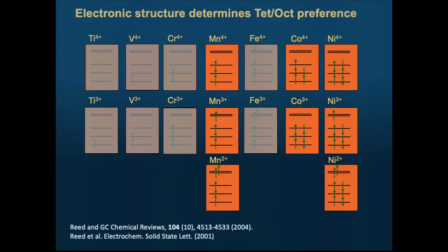What about manganese 3? You think maybe that would be OK. The problem you have with manganese 3 is that it disproportionates. It makes manganese 2 and manganese 4 sometimes, and manganese 2 is terrible. Five electrons, it's a half-filled d shell. This thing moves all over the place, because basically it's ambivalent about its coordination. So those are out, but the one you can use is manganese 4. This is perfect. 3 electrons, if you don't oxidize it, you stabilize octahedral coordination. And now you see where our battery chemistry ends up from. We use manganese 4. We use cobalt 3. This is the perfect ion. You have 6 electrons, non-spin polarized. You have 6 electrons that fully favor octahedral coordination. And indeed, the one element that we never, ever see move around is cobalt 3.